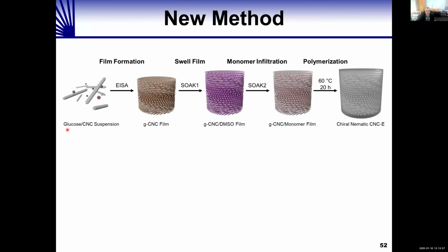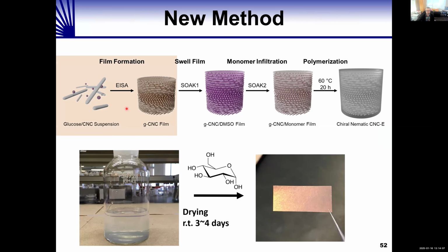We start with a solution of glucose and cellulose nanocrystals in water, and then we allow it to dry. We call that evaporation-induced self-assembly. So all you do is take that mixture of glucose and cellulose nanocrystals, leave it to dry, and you get a colored iridescent film because the cellulose nanocrystals have organized into this helical structure.